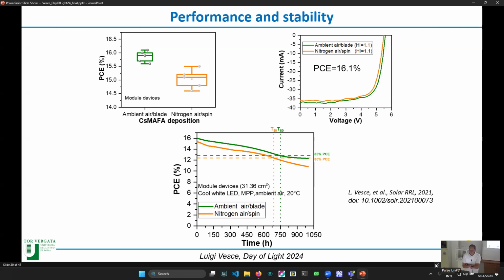Then we made some preliminary aging tests in light soaking at MPPT. Here you can see that the T80 is not so different between the two techniques: 750 hours for the blade coating technique and about 780 hours for the spin coating technique. But it's also important to see the behavior of the trend after the T80. The spin coating is completely going down because the defects start to play a role, and the blade coating substrates are going to be almost stable at some percentage.